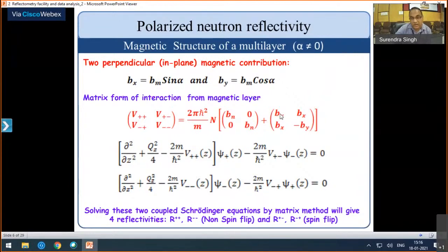And putting this potential again in the Schrodinger equations, we will have this kind of coupled equations, which one can solve like we did for R minus plus. So basically what we have to split is the component of the magnetization vector, and then we can get the four reflectivities from the sample, which will give us the detailed magnetic structure.